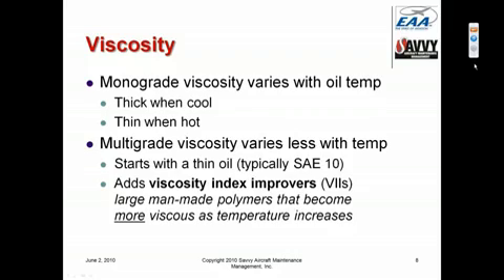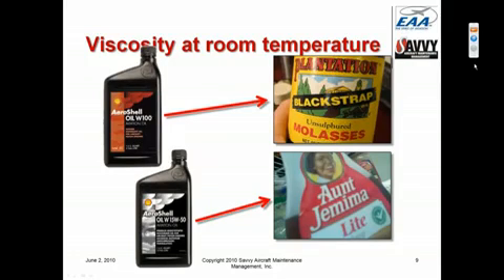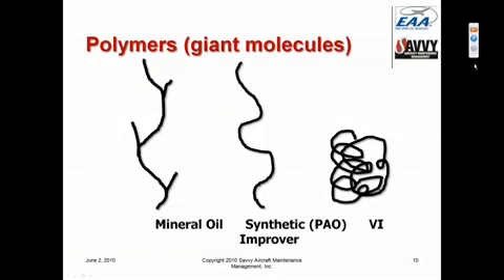Now keep in mind that VI improvers are not lubricants. They're thickeners. They're kind of like cornstarch in soup, except that they have this unique characteristic that they get thicker and thicker as the oil gets hotter and hotter. So at operating temperature, Aeroshell W100 and Aeroshell 15W50 both have basically the same viscosity. They're SAE 50 oils, both. But at room temperature, Aeroshell W100, the monograde, is very thick. It has the consistency of blackstrap molasses, whereas Aeroshell 15W50, the multigrade, is very thin at room temperature. It has the consistency of Aunt Jemima light, or I suppose you could use ketchup versus tomato juice if you prefer.